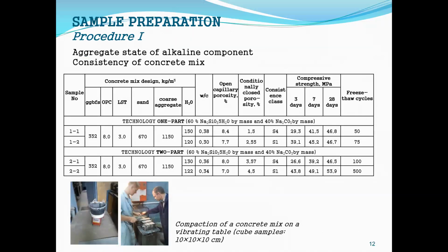It was revealed that consistency of fresh concrete is an important factor of porous structure. Thus, increasing of consistency from class S1 up to class S4, while application of alkaline component in dry form, as well as in liquid form, caused increasing of volume of open pores and decreasing volume of conditionally closed pores. Less volume of conditionally closed pores determines formation of less dense and more permeable structure, which causes deterioration of physical and mechanical properties of alkali-activated blast furnace cement concrete, including freeze-thaw resistance decrease.